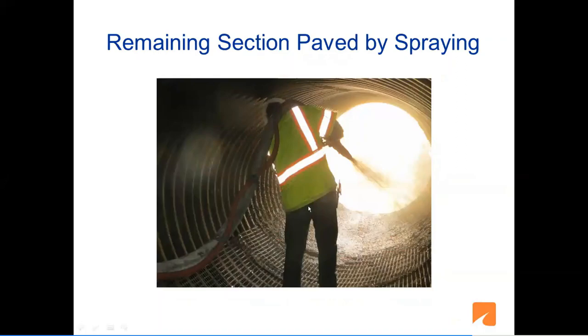So the remaining 64 feet is a pretty large section. There we placed it by spraying. There is a shotcrete nozzle here. So there is the pump line. So we sprayed it onto the invert, as you see, very thin layer.